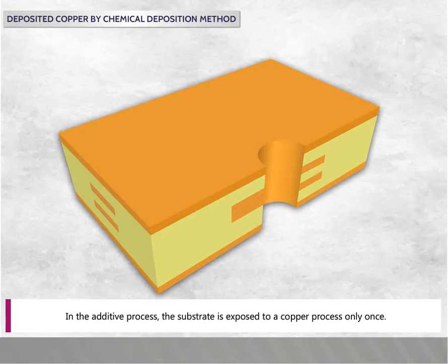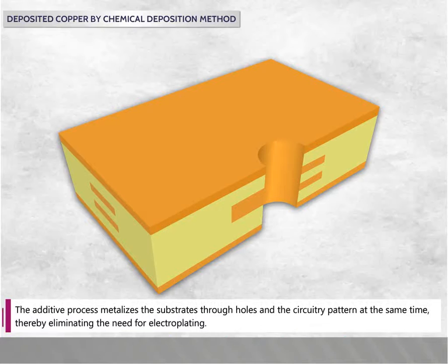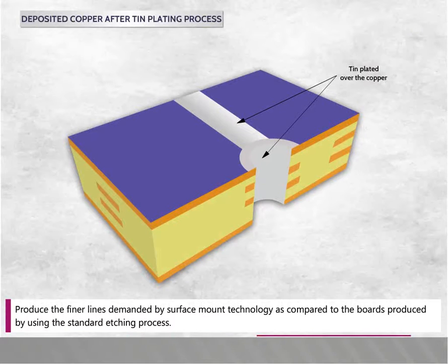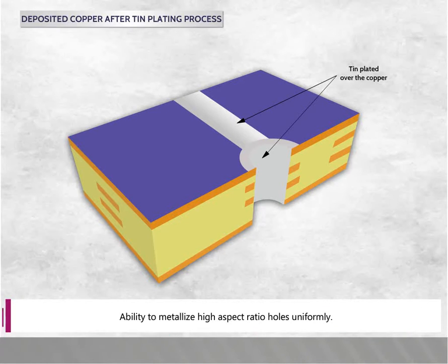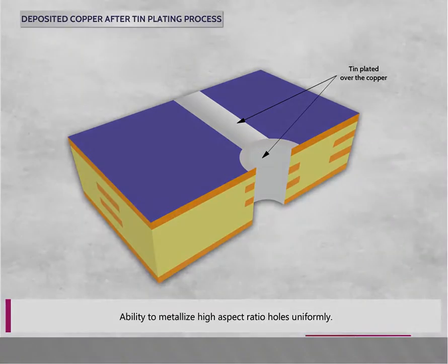In the additive process, the substrate is exposed to a copper process only once. The additive process metallizes the substrate's through holes and the circuitry pattern at the same time, thereby eliminating the need for electroplating. Deposited copper after tin plating process. It can produce the finer lines demanded by surface mount technology as compared to the boards produced by using the standard etching process, and has the ability to metallize high aspect ratio holes uniformly.